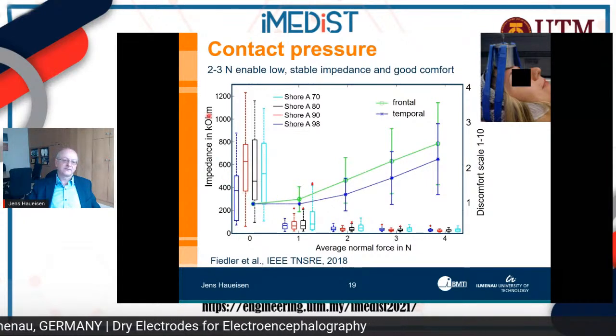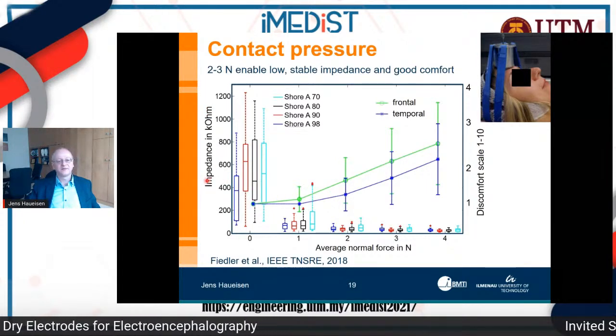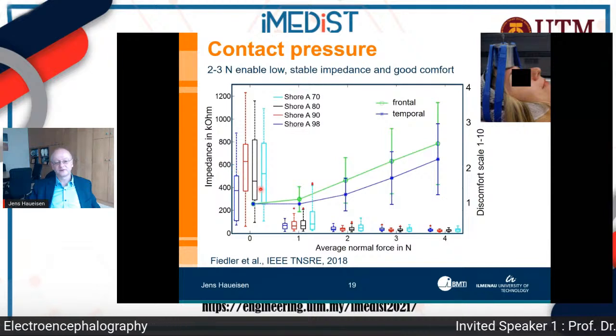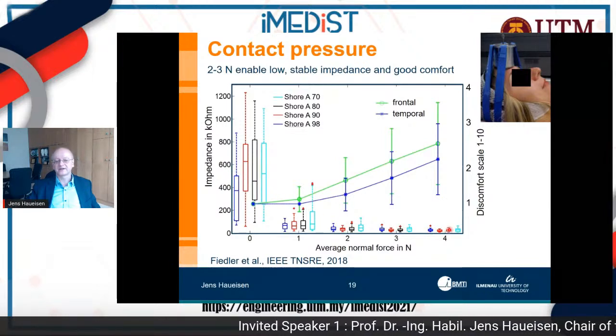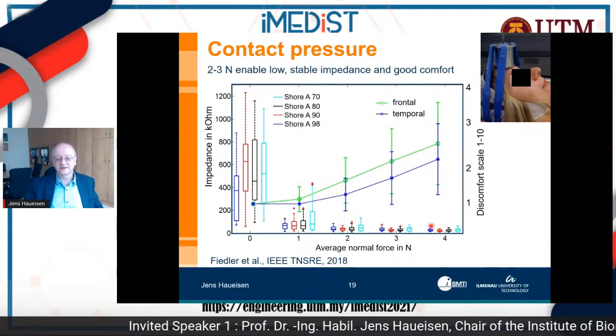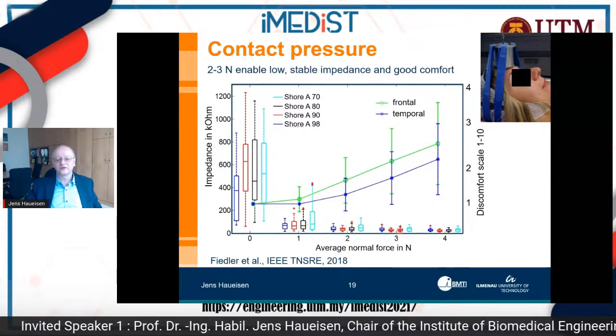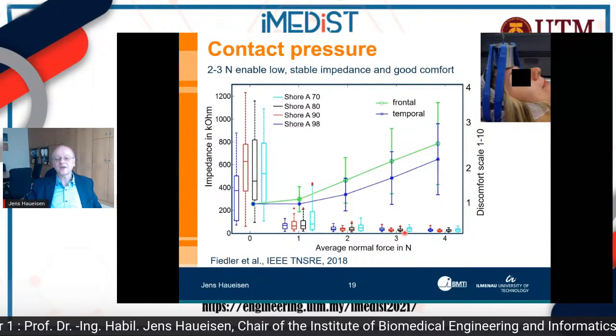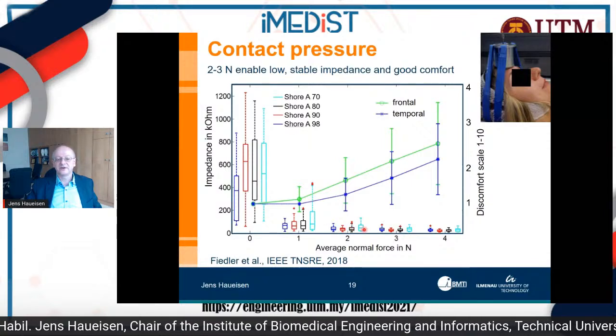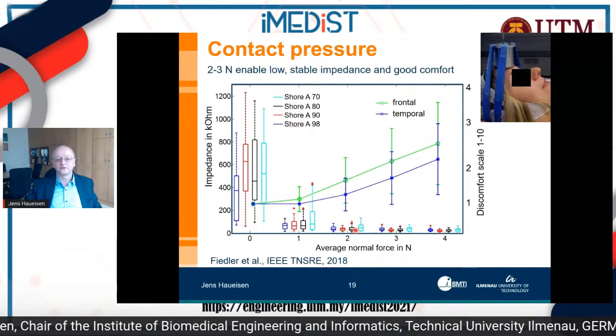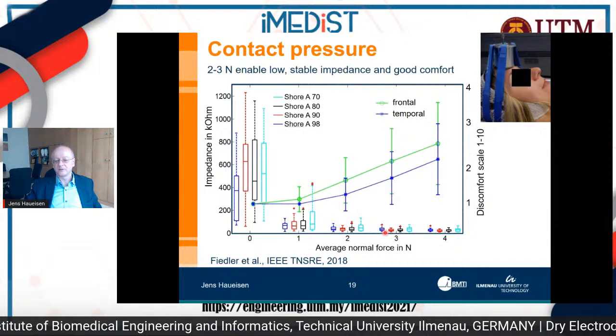On the other side, when you see the impedance, this impedance is of course dropping as you increase the force, and that is also expected. And what you can see is that already with 2 or 3 Newton force, it is not very difficult to reach good impedance values anymore.